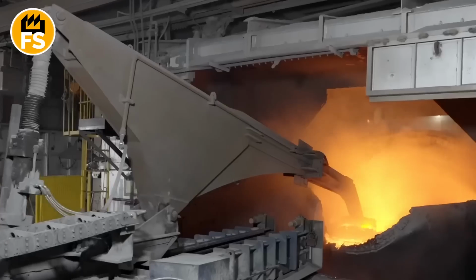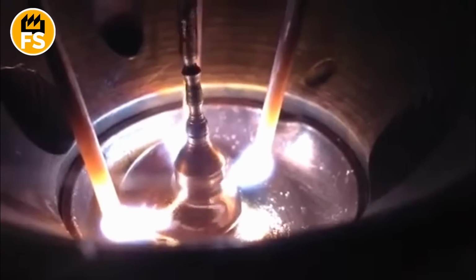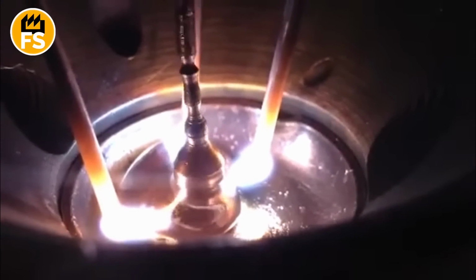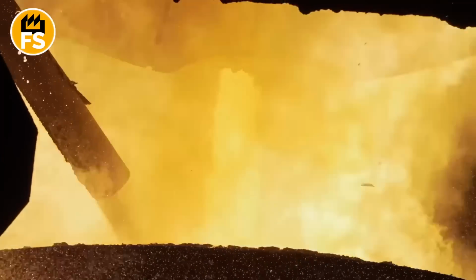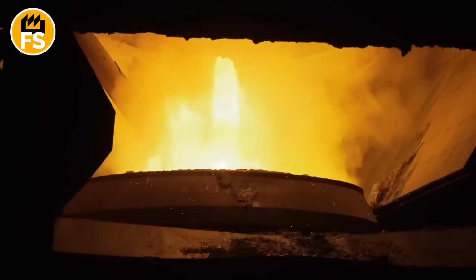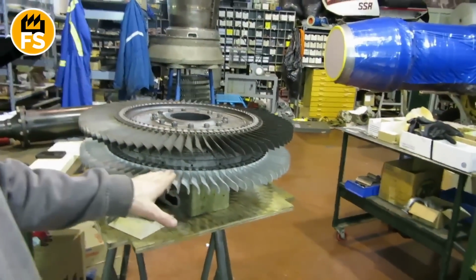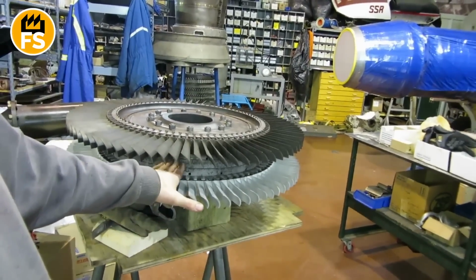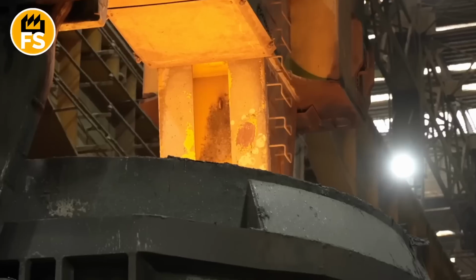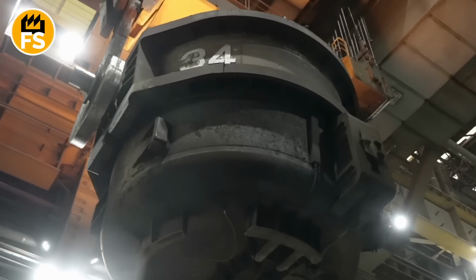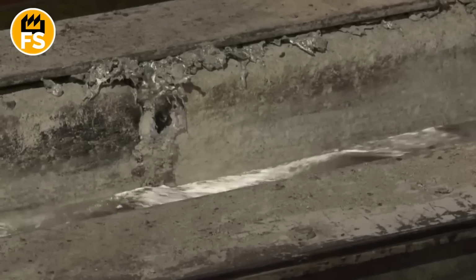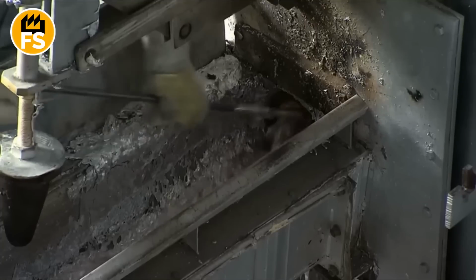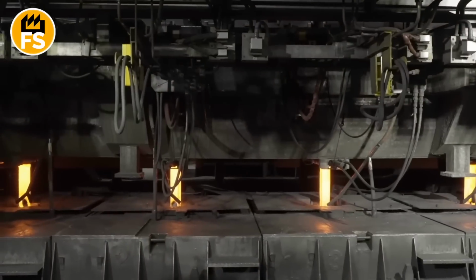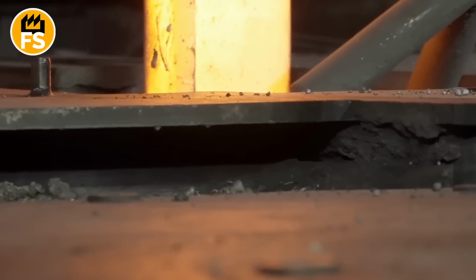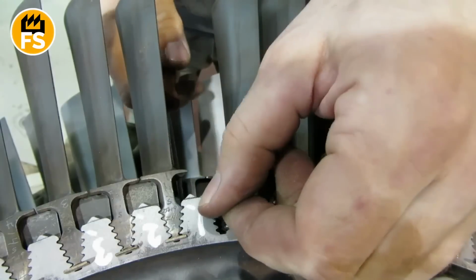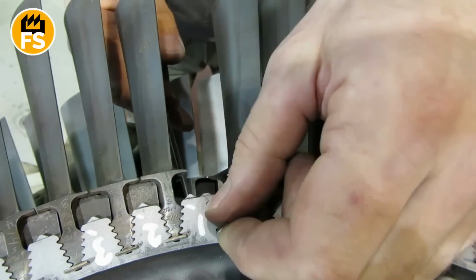Single crystals are grown through a slow cooling process. The mold filled with molten metal is gradually lowered into the cooling zone of the furnace. This process can take days, but the result? A blade that's incredibly strong and durable. Once the metal cools, the ceramic mold is broken away, and the blade undergoes meticulous polishing. A special heat-resistant coating may be applied to help it withstand extreme temperatures even longer. And yes, each blade is inspected individually. Even the slightest defect means it won't make the cut.